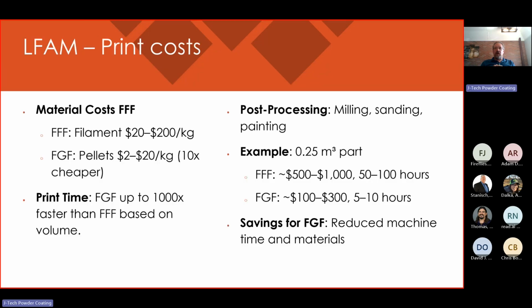So let's talk about economics of large printing. Your FFF filaments are costing between $20 to $200 per kilogram. FGF pellets are $2 to $20 per kilogram, up to 10 times cheaper, and it's really because they skip the filament production process. FGF's high throughput can be 1,000 times faster, but that's at the cost of resolution. For a 1/4 cubic meter part, FFF might cost $500 to $1,000, take 50 to 100 hours, while FGF could cost $100 to $300 and take 5 to 10 hours. Significant cost savings. With near net shape prints, post-processing like milling or sanding does add cost, but it's often minimal depending on the size. LFAM really saves money by eliminating the traditional tooling costs for production of unique models.